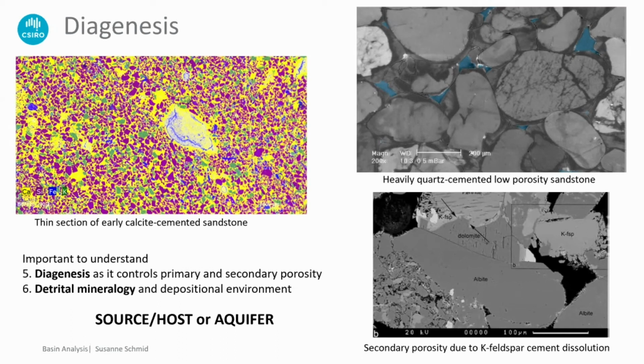The third example is when you have one of those dirty lithic arkosic sandstones that have a lot of feldspar, a lot of lithic fragments. They usually also come with a clay coating around the quartz grain because it's just the nature of how they form. They're much better. They have good porosity, but because they have this K feldspar component, K feldspar cements grow really early, at early temperatures, and it's easily dissolved at the same time. So you have a good primary porosity, but you also have an excellent secondary porosity. And you can apply the same principle to your host if you have a feldspathic host or lots of feldspar cement in your host because it has a lot of volcanic components. That secondary porosity is again very crucial for mineralizing processes if it's an epigenetic system.